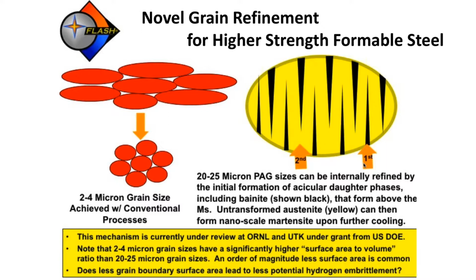So if you could imagine this 20 to 25 micron grain size as austenite up at 1100 degrees C, or near 2000, 2100 degrees Fahrenheit. As you quench that and you're cooling the steel, transformations occur at different temperatures. From 650 C down to 550 C, or roughly 1200 to 1000 degrees Fahrenheit, we actually form bainite. And the bainite is represented by the black triangles in our yellow grain.